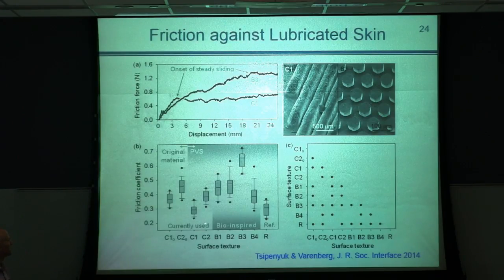And what we can learn from here is that, for instance, Schick shows the same friction as a smooth surface, so there is no improvement due to the surface structure that they sell. Gillette performed a little bit better, but it showed similar results to the worst biomimetic surface texture that we had, while the best biomimetic structures performed significantly better than commercial razors that are used nowadays everywhere.